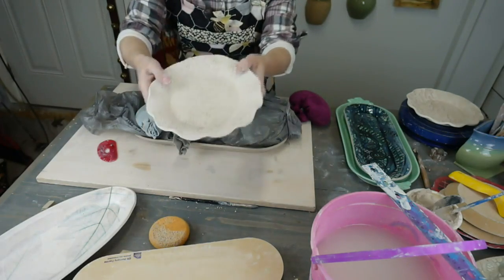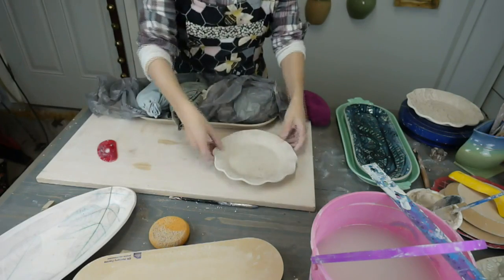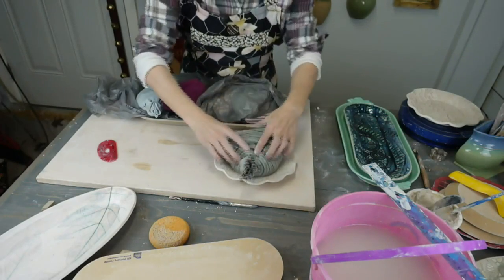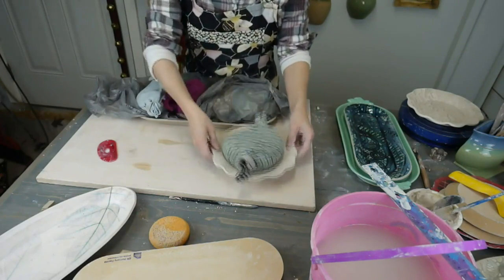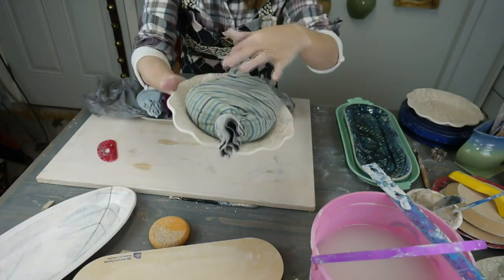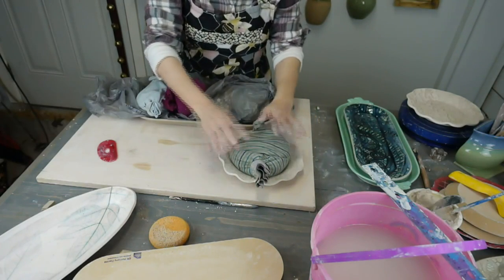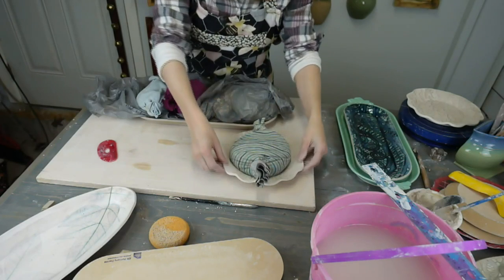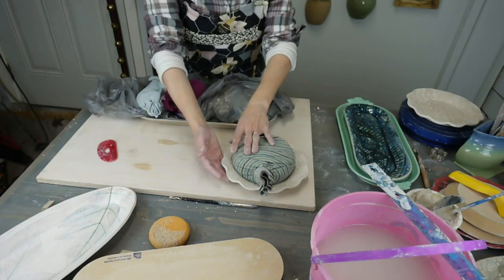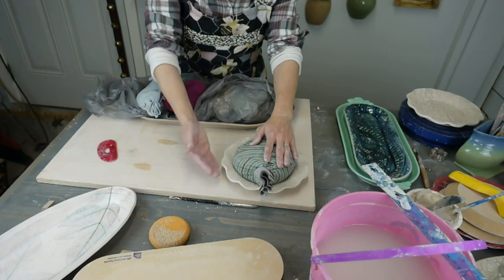To dry these plates, I just put a couple of weight bags that are big enough to cover the entire bottom. Do you see how the weight bag is covering all flat surfaces? It's keeping the foot firmly on the board — that's what we're trying to keep down. If one side is curling up more than the other, pay attention to your plastic covering during drying.